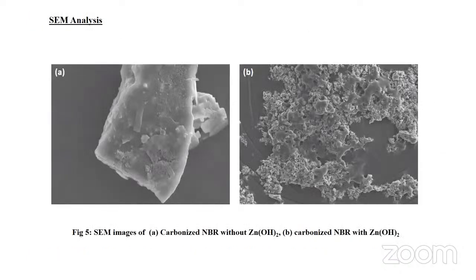In the SEM images, in the first SEM image, we cannot see zinc oxide deposited on the carbon surface, but in the second image, we can clearly see the zinc oxide particles are deposited on the carbon surface. This structure is responsible for the fast decomposition of water molecules on the surface and increases the conduction mechanism.